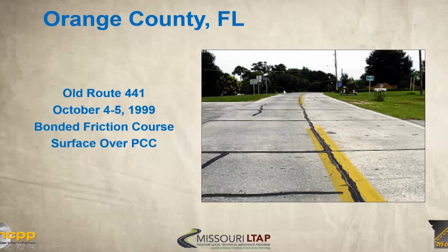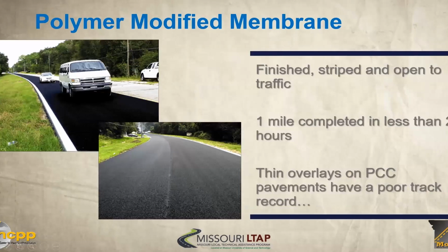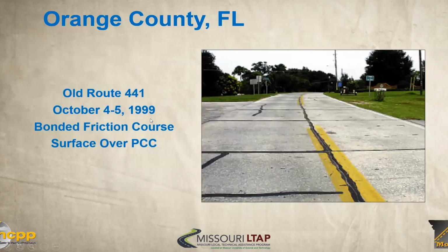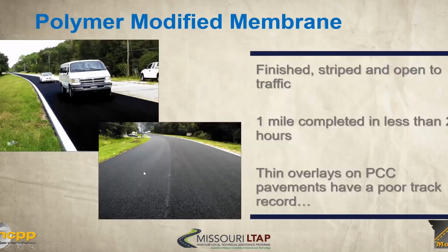And this is a concrete pavement, a very old concrete pavement in Florida near Orlando. And you can see that as we were placing this on the jointed concrete, it was crack sealed first. It's very quick. And for something that's normally not done, meaning we don't usually do very thin overlays on top of concrete because of the fear of delamination, this is very effective. We completed the test section in less than a couple hours.